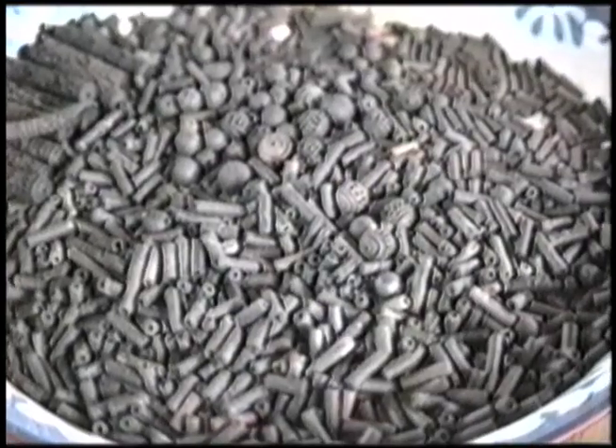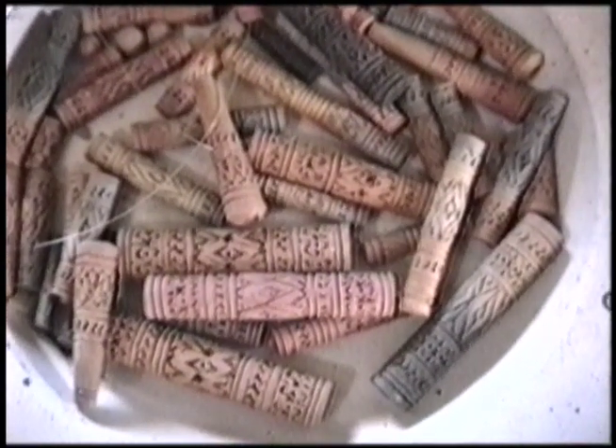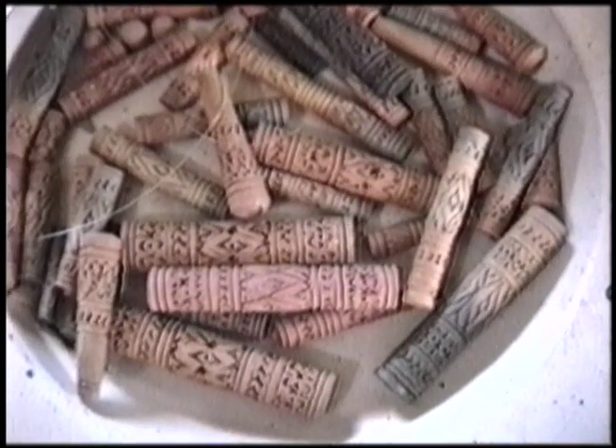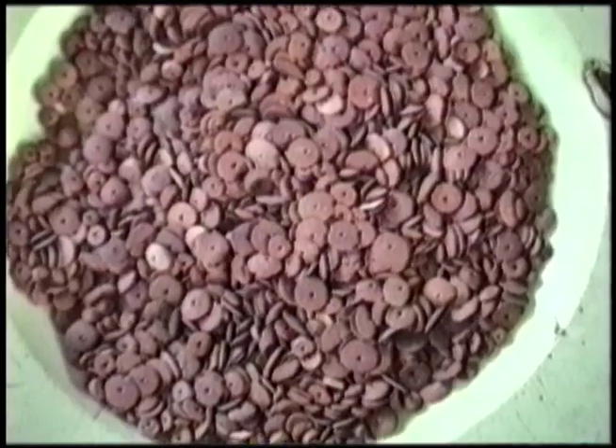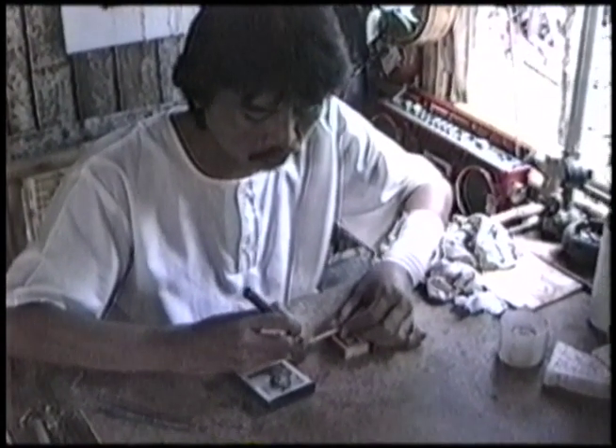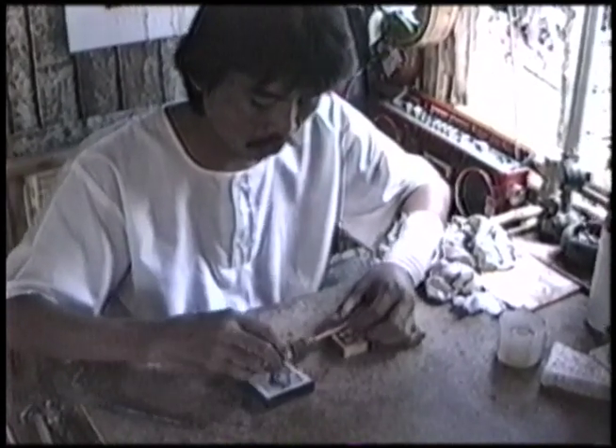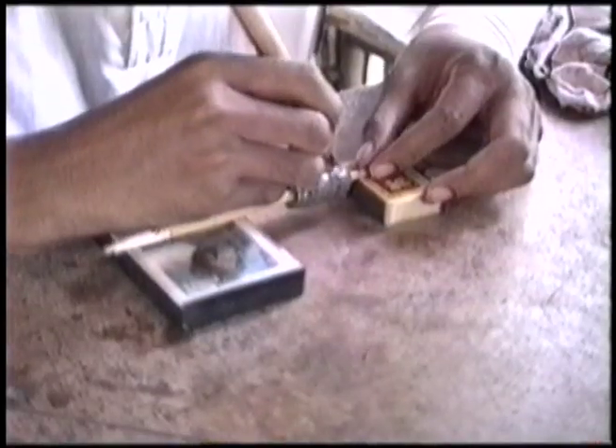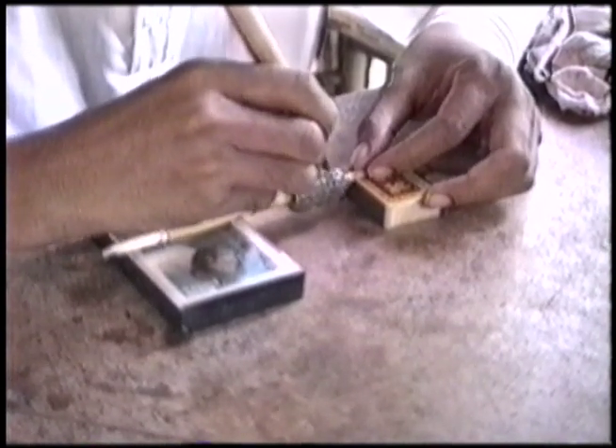The finished beads, when fired, will be strung into necklaces and other jewelry. The perfect tourist wear, these necklaces are small, cheap, handmade, and unique. One style of beads is produced to fire natural black, red, and orange and gray colors. The black and gray colors are produced by burying the beads in rice hulls as they are fired. The other colors are produced by varying the firing temperature.